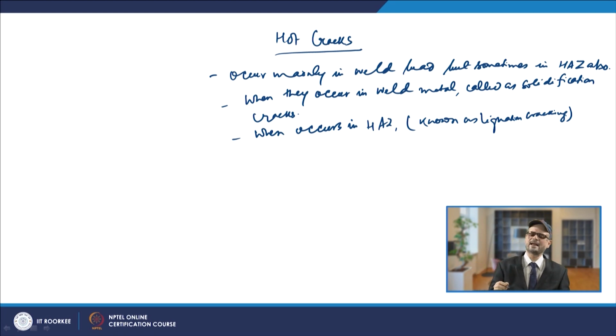So, solidification cracks are there in the case of weld bead. They occur basically when the metal is very hot. When we talk about the area of weld bead, the temperature is very high, just below the solidus temperature. That will normally be the case for hot cracks or solidification cracks. They will normally be interdendritic, following the random path of grain boundaries along the segregated concentration of impurities.